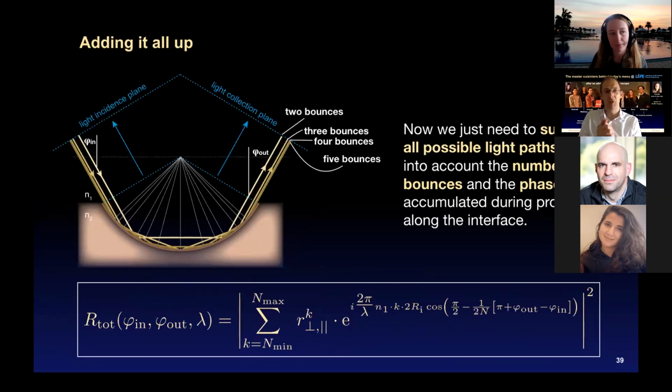We split the light into these different paths, and each path gets a little bit of a different shift. And then when you combine them on the outgoing side again, you can write a simple formula down that accounts for the phase change upon reflection, this thing that I put my pointer around here. It accounts for the phase shift, this complex exponential, for the whole path length of each path. And then we just sum over these paths. And since we measure intensity, not amplitude, we just square this up and get our reflectivity.